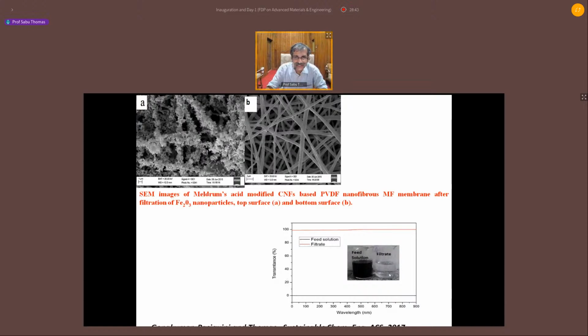This is the feed solution, which is very black because you have lots of iron oxide particles. And you look at the transmittance, light cannot transmit because you have lots of nanoparticles. There is a lot of scattering. When you do the filtration process, you can remove all the particles. All the particles are retained by the filter, and you get good water. Look at the transmission; it's almost 100%. So my message is, nanocellulose coated filters are extremely beneficial to remove suspended particles from water.